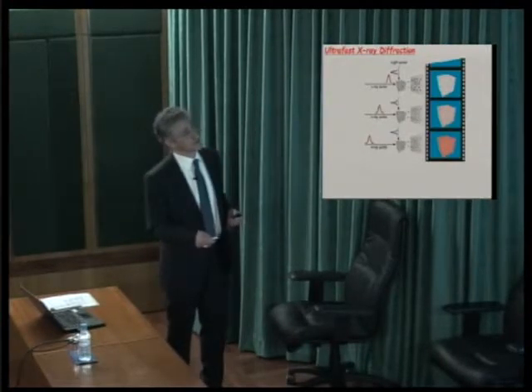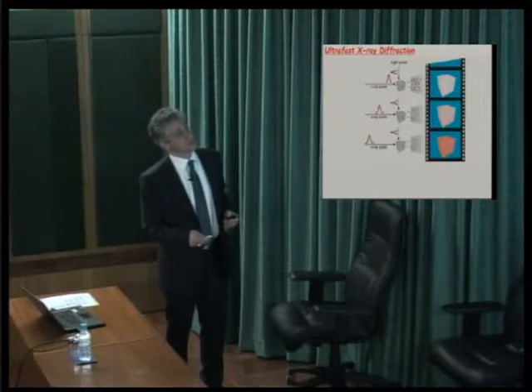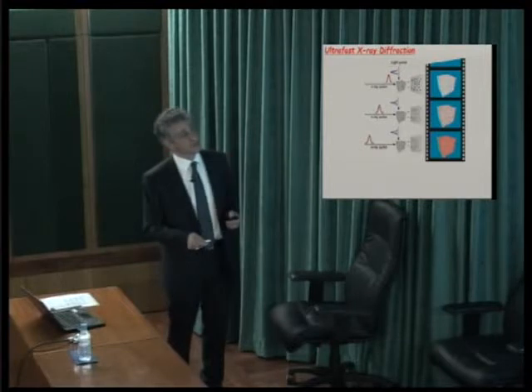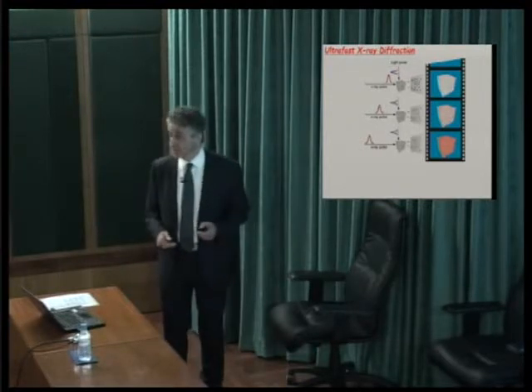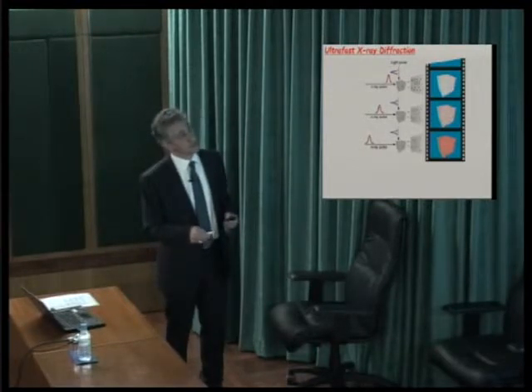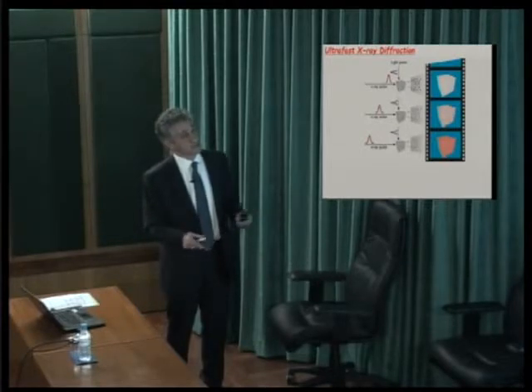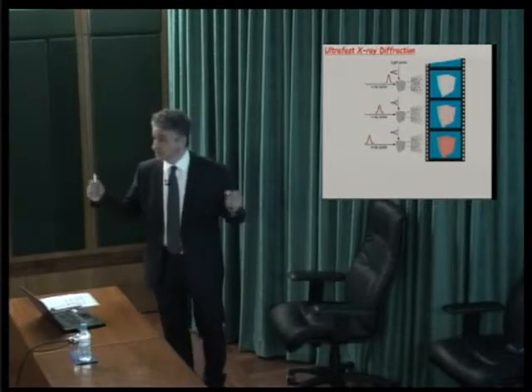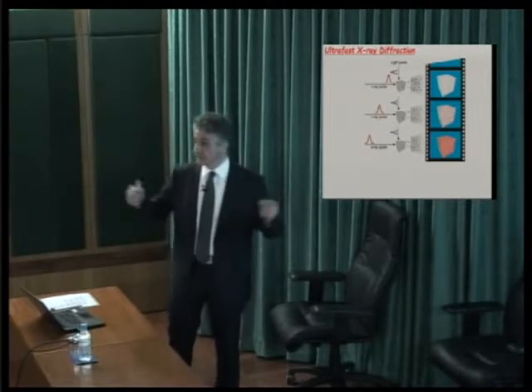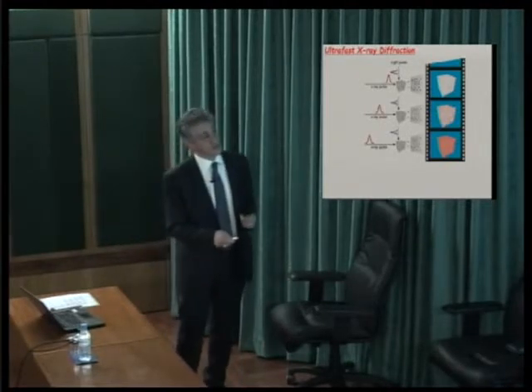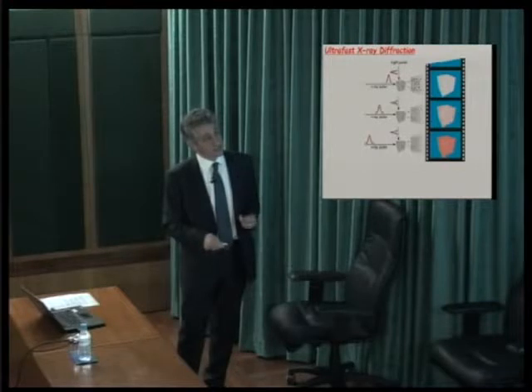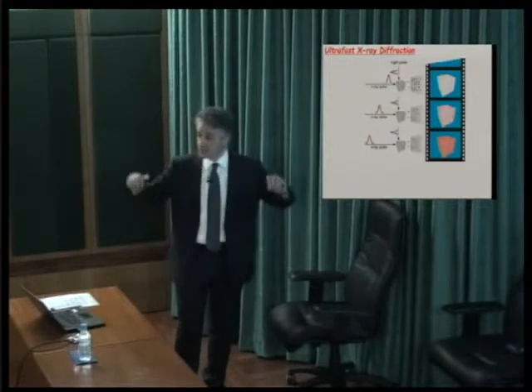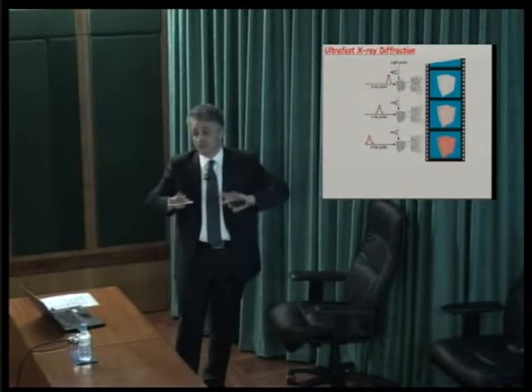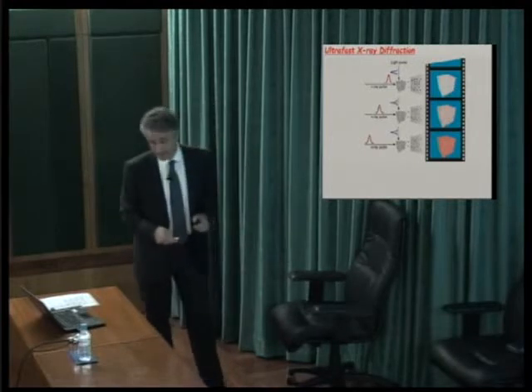So you have a crystal, you have an X-ray pulse. If you have no excitation, you can get the nice Bragg spots. But now if you perturb the crystal at time zero, that means when the two pulses arrive together, at the beginning you see nothing, and then depending on what process you trigger, you could have coherent phonons, you will see these Bragg spots oscillate, or you could have a melting of your crystal and then you see them blur away, and eventually you can follow recrystallization.